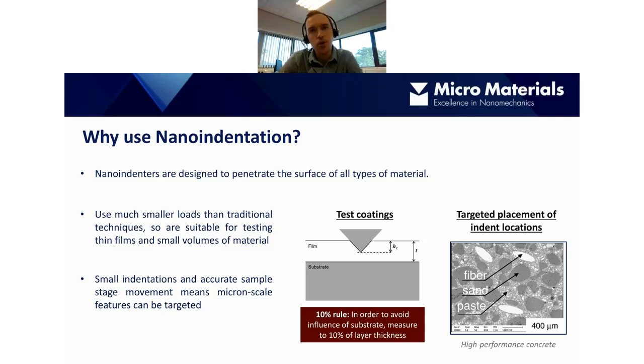And the second key reason is that we can use the nanoindenter to target indentations into very precise locations. That means we can characterize mechanical properties of individual phases within a material, rather than doing just one big indentation. The example shown here is a high performance concrete sample. You can see there are different phases within this material: the fiber, sand, paste. Most nanoindenters come with an optical microscope, and we can use that along with the precise movement of the sample stages to position indentations within these different phases. So we can assess what we call the local properties of these phases, as well as the overall response of the material.